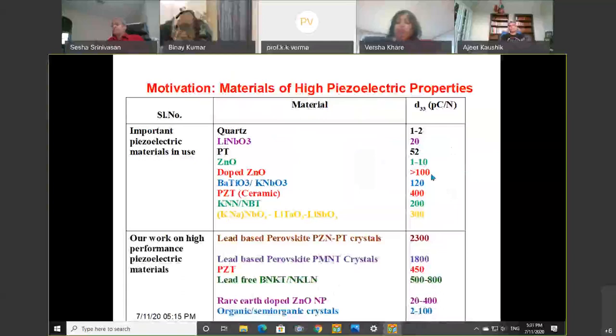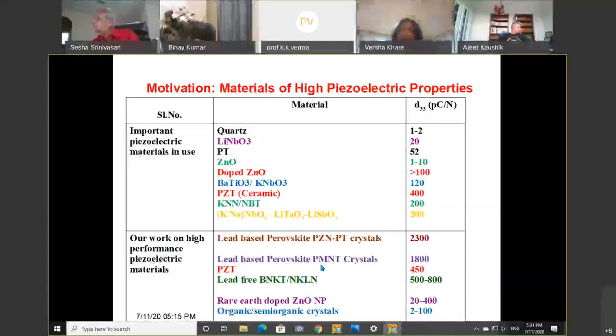And there are some lead-free and lead-based materials. These are the materials which we are making in our lab. They are PMN-PT crystals, for which we have achieved above 2000, close to 2000. PZT we have also grown up to 450. Then there are lead-free materials, because in many applications, particularly household applications, we try to avoid the lead part. For lead-free materials, we have achieved up to 500 to 800 d33. So you can compare that with respect to quartz and PZT. The materials we are using have much better d33 values. What does it mean? If you use a material which has a higher piezoelectric constant, your efficiency and working range will be much better when we use a device made up of these materials.